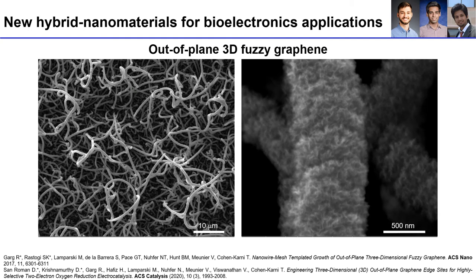In the last several years we reported our unique technique to generate nano-pipe brush-like structures of out-of-plane grown single-to-few-layer graphene flakes from a template of silicon nanowires. You have a surface of two by two centimeters covered by these fuzzy wires. Zooming in on a single wire reveals the fuzziness of single-to-few-layer graphene.